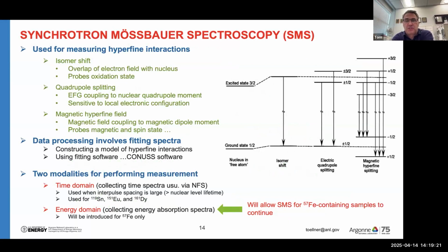For the second technique, the Mössbauer spectroscopy, here we're going to look at measuring the hyperfine interactions. These are interactions between the nuclear moments and the fields generated by the electrons. One is the isomer shift. This results from an overlap of electron density at the nuclear volume, and so it's very sensitive to s electrons. And as a result, it probes oxidation state and valence.